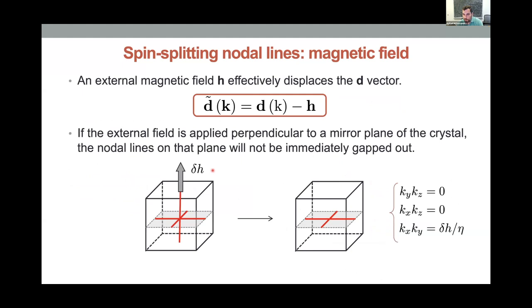And let's consider the most common perturbation, which is applying a magnetic field. If the field is applied and I still keep one of these mirrors, it means that the nodal lines that are sitting on this mirror plane will not be gapped immediately. So in this example, I applied a magnetic field along the z direction. You can interpret this as a displacement of my d vector.